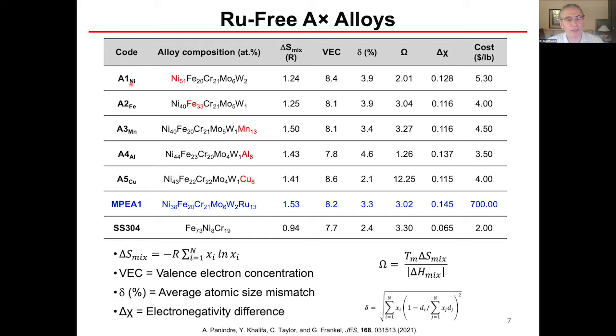So you can see that for nickel and iron, they only have 5 elements, where the nickel concentration or the iron concentration has been increased and the ruthenium has been removed. And then you see we've added manganese, aluminum, or copper in these other alloys in A3 to A5. Now I'm presenting here these metrics that Nick flashed through, and I won't spend much time on them either. This entropy of mixing, I don't think that anyone these days thinks that high entropy is critical in the corrosion performance at all. But indeed this 1.5 R is reached only by a couple of these alloys.